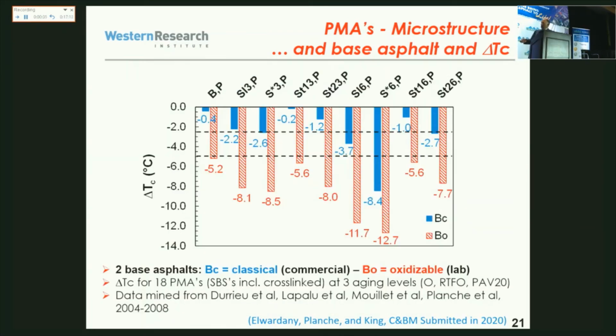What also plays a role, and I already said that, is if you change the base asphalt. Here there are two sets of binders with two base asphalts. One is the blue one, the other the red one. The red one has a very low delta TC, the other one not so low. And when it's modified, of course, there is a lower delta TC with the polymer, but it's highly impacted by the base asphalt. So when you make a polymer modified asphalt, be careful what kind of base you use.